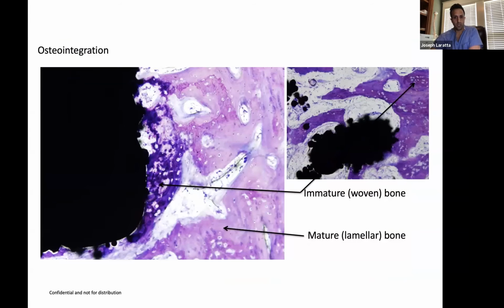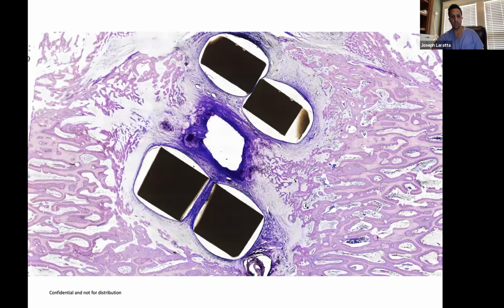This is just looking at things a little bit closer, and you can see this purple is this immature woven bone, and that this pink is the mature lamellar bone. And you can see that there's early osteointegration of immature woven bone and in an intramembranous type of formation on the cage itself. Now, when we look at PEEK, it's a stark difference, right?